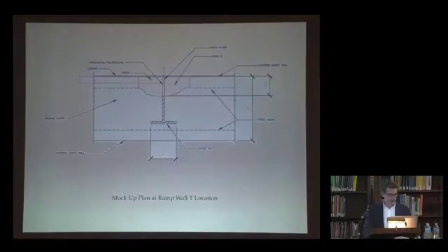So for our on-site mock-ups, as I said before, the two final product systems were carried out and left in place to be monitored and measured on the building. The idea with this repair was that we were going to create expansion joints at the gunite wall tees, where the building determined they were required, but Wright didn't want them to be. The size of the opening would be determined based on the amount of measured movement in a given location from those sensors, and careful consideration was given to preventing the repair from affecting the shape of the exposed surface coating as the building expanded and contracted.